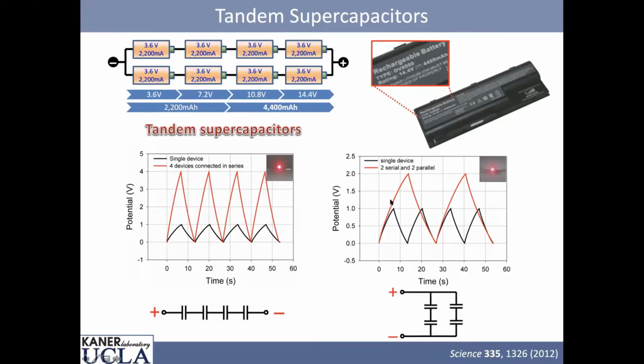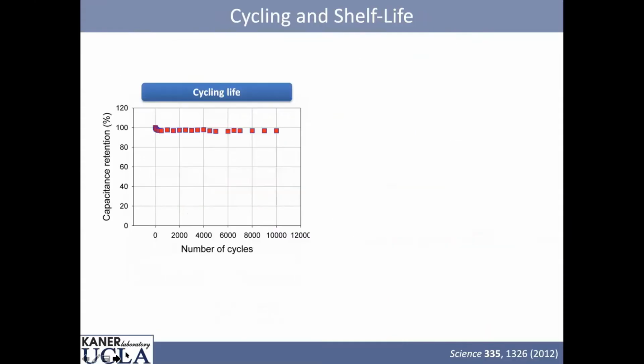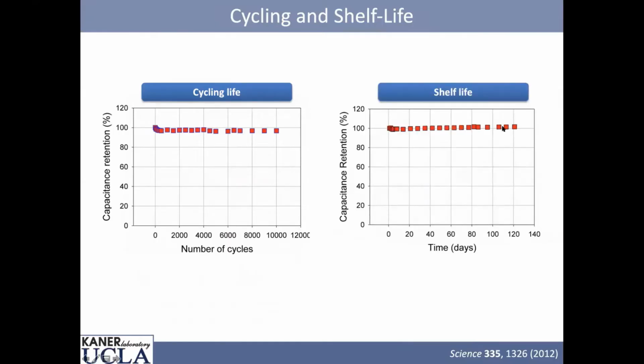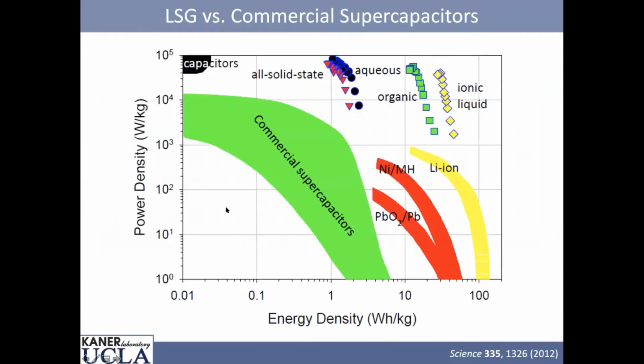If you've seen these before, you look for an IR drop here, and there's almost none. So these are really good devices with very little internal resistance. They have very good cycle life. This is 10,000 cycles, and you'll see the capacitance retention is good. They have good shelf life. We ran these for 4 months, and you can see very little loss. So what's the problem? Well, if you put them on a Ragone plot, they're better than any commercial supercapacitors. And if you go to ionic liquids, they start approaching rechargeable batteries, but they're not there yet.